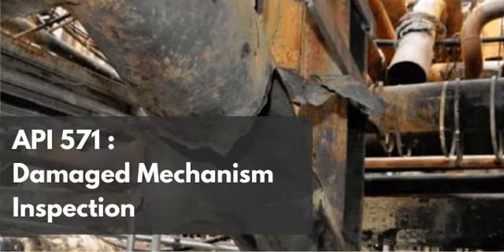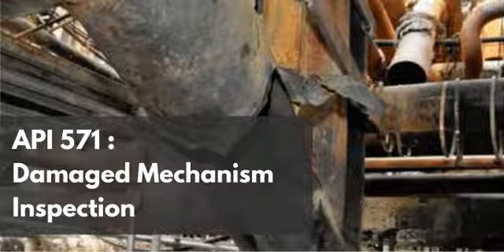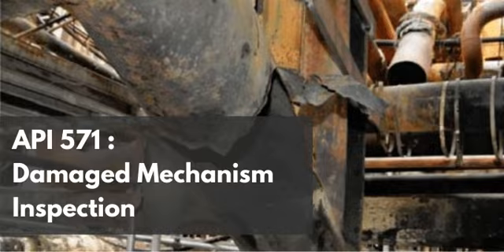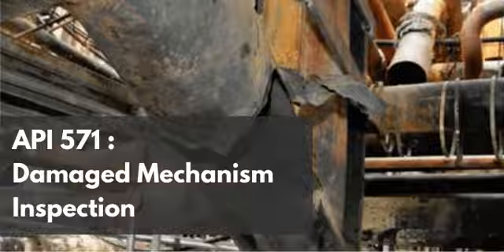But then we have the second type of morphology, which is localized under-deposit attack. And this one seems much more sinister. Oh, it is significantly more insidious, largely because it happens out of sight and it accelerates rapidly. Because of the deposits. Right. If you have deposits forming on the internal surface of the metal, and these could be from previous corrosion products, iron sulfide scales, or other particulate matter carried in the process stream, the environment directly beneath that deposit becomes physically isolated from the main bulk fluid flow. So the deposit acts like a little roof. Exactly. It forms a microenvironment.